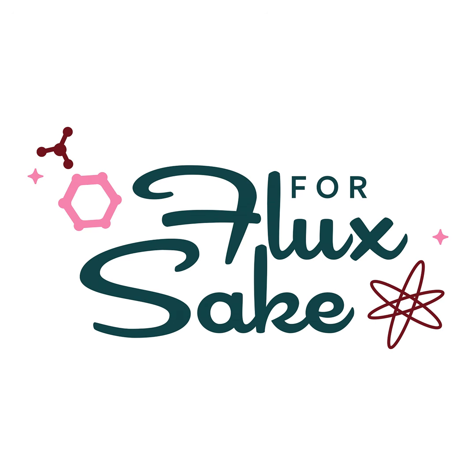The next one that people will find interesting is an iron-based glaze underneath a glaze that is not iron-based. This occurs because iron decomposes. We've talked about how iron goes through what we call thermal decomposition, which is at cone 4, iron breaks down and releases oxygen as a byproduct, and this makes bubbles inside the glass. Those bubbles cannot rise in the glass, but what they can do is swell until they reach the surface and then pop. And that will create a level of distortion because when it swells, it'll literally push the top glaze aside, and then you'll get these spots of the bubbles from the undercoat. And that's most of what glaze layering is, basically working with those two reactions. Glazes homogenizing together.